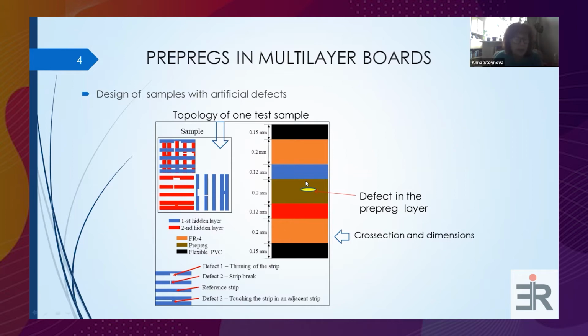This complicates the task, firstly, because due to the specifics of the PCBs, defects of the same size and depth may be located under different layers with different thermophysical parameters. That is, the environment in which these defects of Prepreg are located has a known anisotropy. All performed thermographic examinations of composite materials to detect defects look for the appearance of temperature differences on the surface of composite materials as a consequence of its impaired anisotropy due to the existing defects. In our case, the task is more complicated because the Prepreg layer is hidden under the surface of the PCB under a different number of tapes and layers.